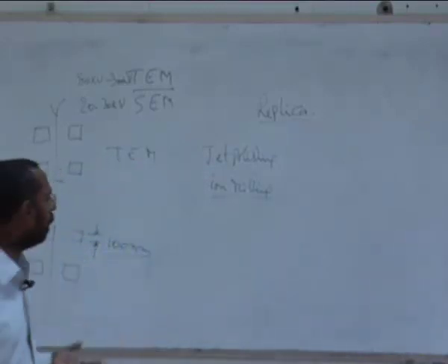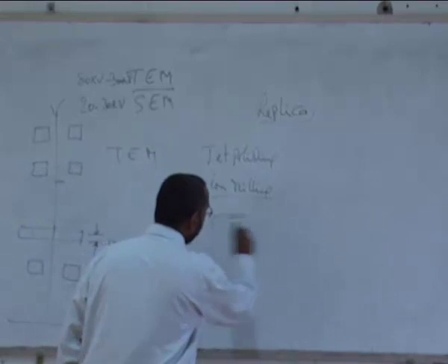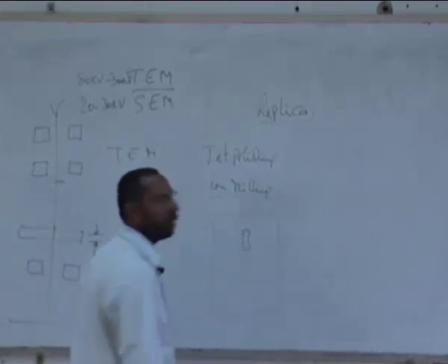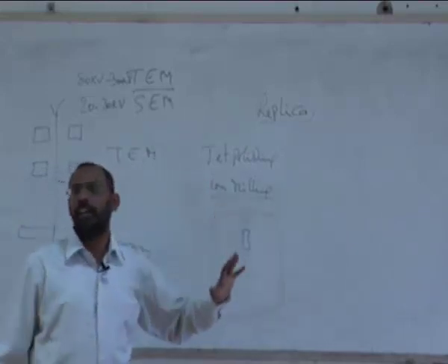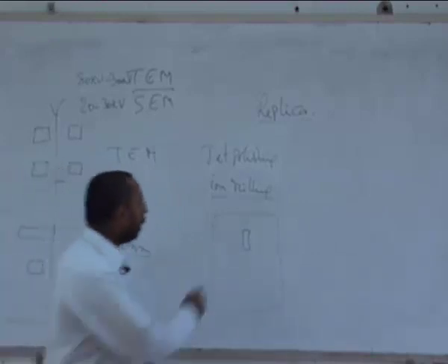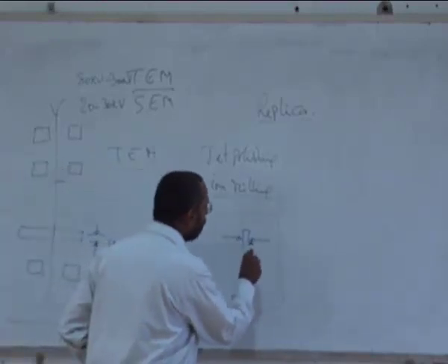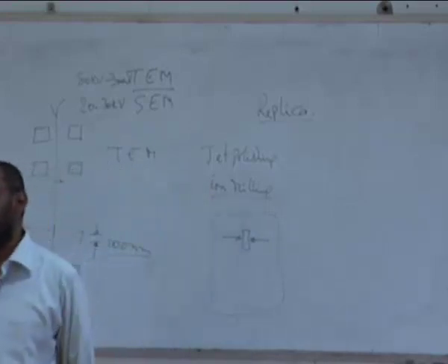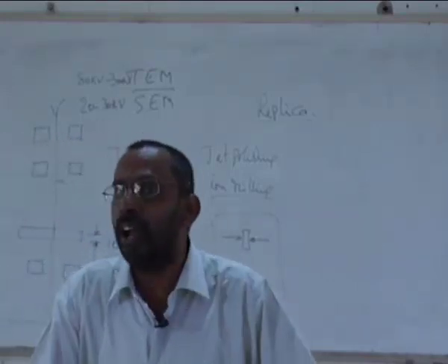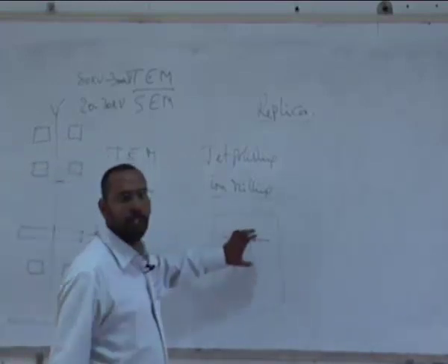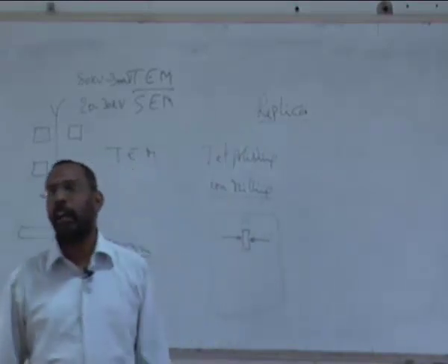And in ion milling, basically because you are putting your sample inside a chamber which is completely evacuated and filled with argon, and that argon is allowed to form a beam on the sample to sputter away the atoms. As a result, the chance that the sample is exposed to oxygen is not there. So all reactive metals are usually done by ion milling, though in principle they are conducting and they can be prepared using jet polishing.